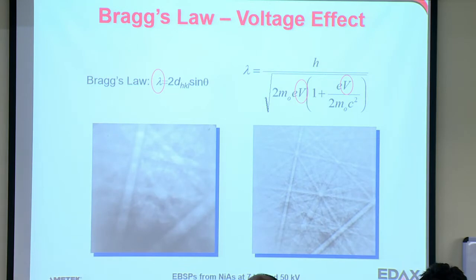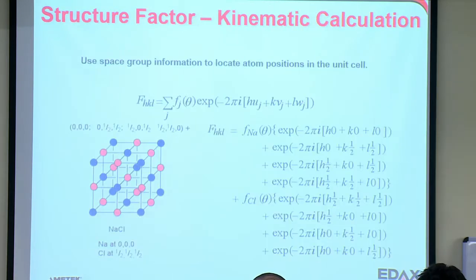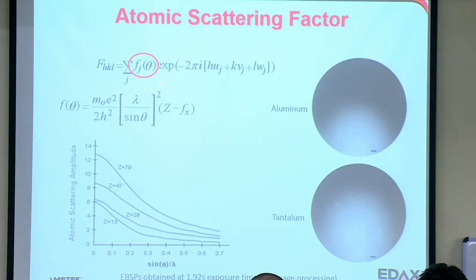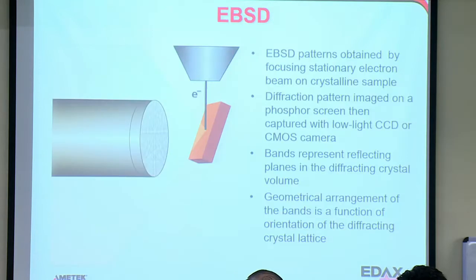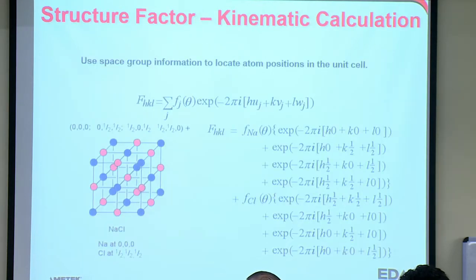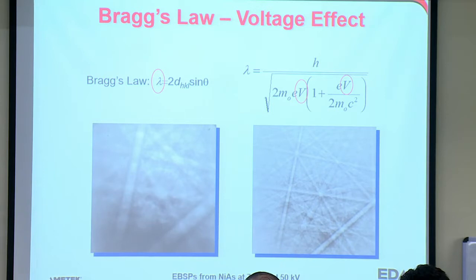So some things to look for in the patterns. Remember, I mentioned Bragg's Law. No, that's not the right one. I'm going the wrong direction, sorry. Here we go. We have Bragg's Law, which is lambda equals 2d sine theta. d is the spacing of the atoms in the atomic plane. Theta is the incoming angle of the electron relative to the plane. Lambda is the wavelength of the radiation. And you calculate the wavelength with this lovely equation here. The important part here is the electron voltage, so this is the kV that we can see on our microscope.